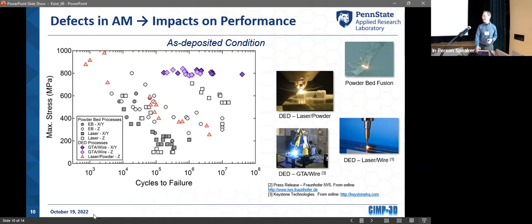This is an example of a fatigue graph. What I'm doing here is I took literature data, again for titanium alloy, and plotted the max stress of the fatigue cycle versus how many cycles it was able to obtain before failure. Just for reference, for Ti64 the fatigue limit is determined to be around 600 megapascals. A lot of additive manufacturers are able to achieve that 600 megapascal fatigue limit in this blue region, but a lot of the literature data was not. And probably what's causing the issue is defects that are causing significant failure in these processes.